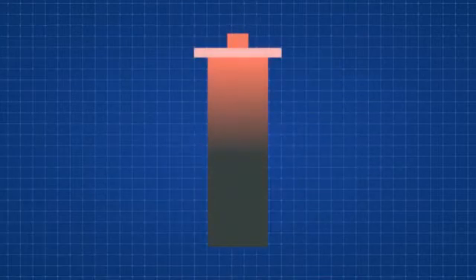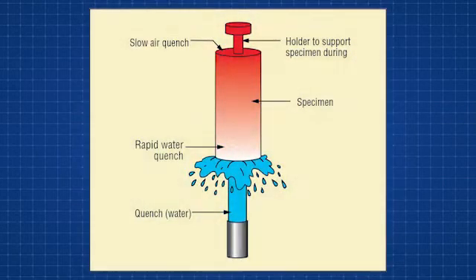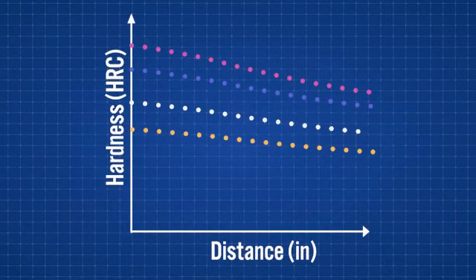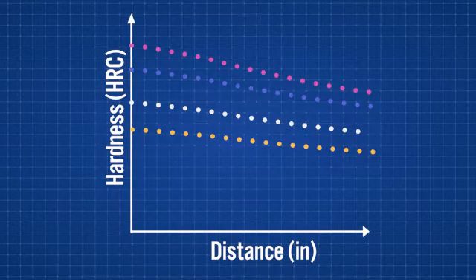In specimens where the cooling rate varies across the length, you can expect them to have different hardness values across the region. The Jominy end quench test is commonly used to characterize the fundamental hardenability of alloys. The test uses end quenching, where water is only applied to the very end of a cylinder, to produce a continuously decreasing quench rate along the length of the cylinder. Very near the end, the material will experience nearly instantaneous quenching and will thus have the maximum achievable hardness. Material along the cylinder will cool more slowly with increasing distance from the end and will thus be progressively softer. The objective for this lab is to produce hardenability curves for various alloys and to describe the effects that carbon content has on hardenability.